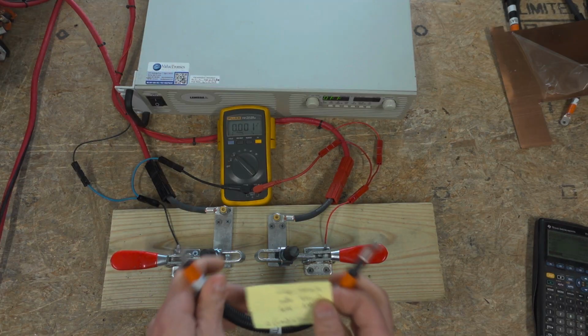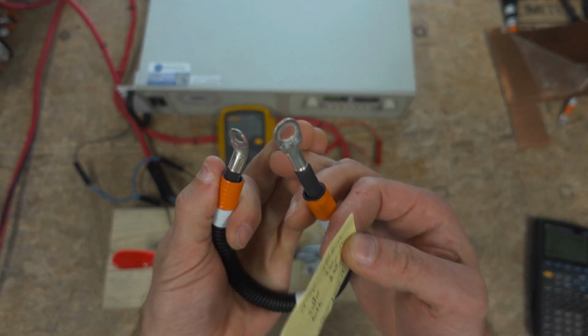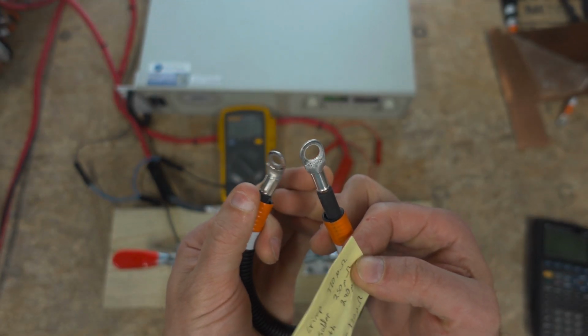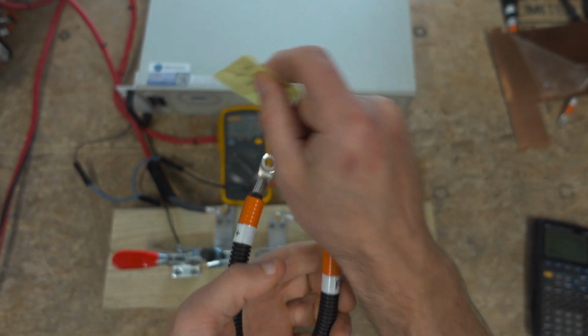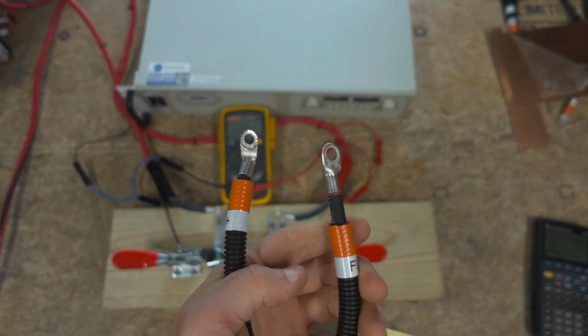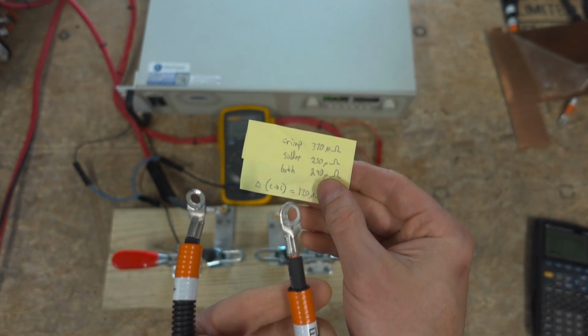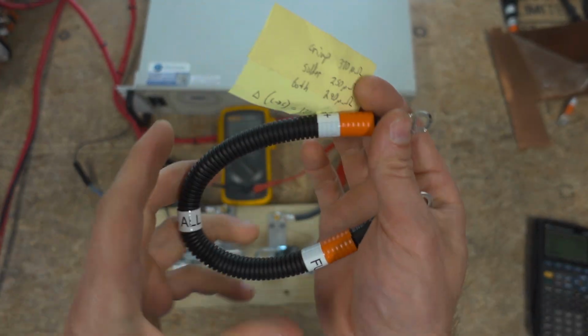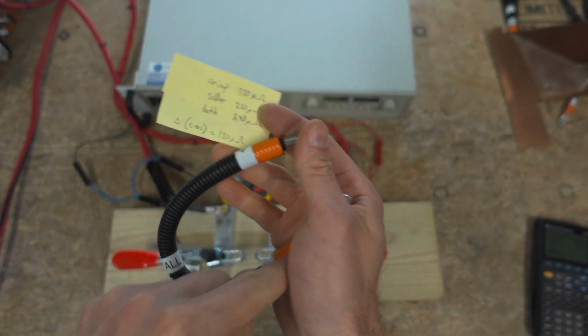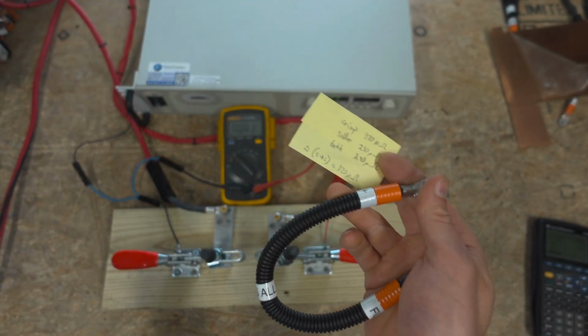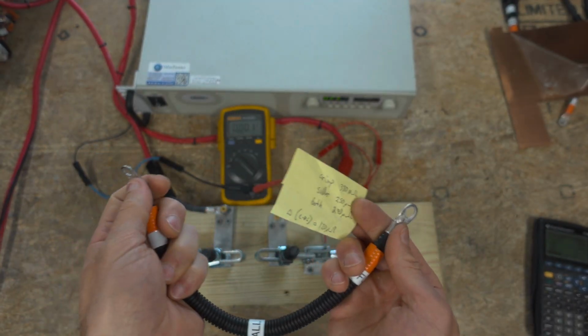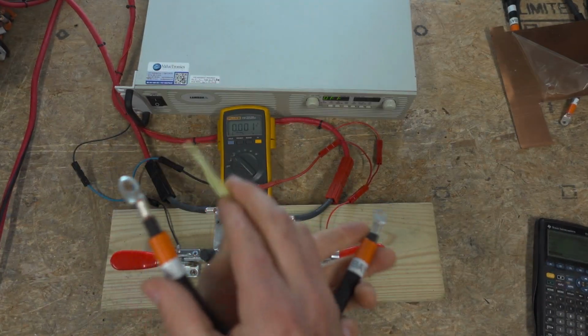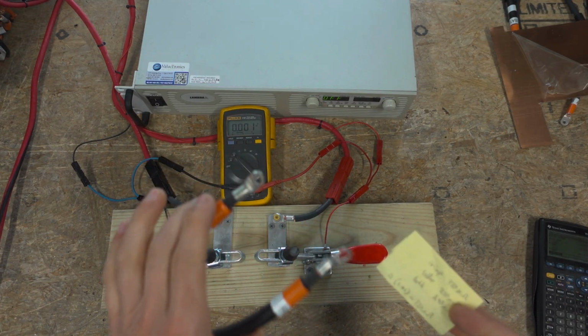I don't have a soldered thing. I don't solder cables. There's no reason to. It's wild to think that you need to. It's like there's a zero-sum game or something in that other video, like if you crimp, your resistance will be higher than soldering. And it's like, no, if that's an issue, if you can't handle the extra 2.7 watts due to this delta from their test data, you need to use a thicker terminal. You need to use thicker cabling if that's an issue. It's not, right? Pushing 150 amps intermittently through a 4-gauge wire like this, no problem. You can do that all day long.